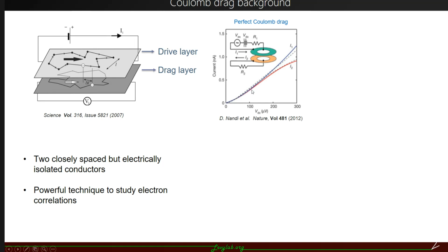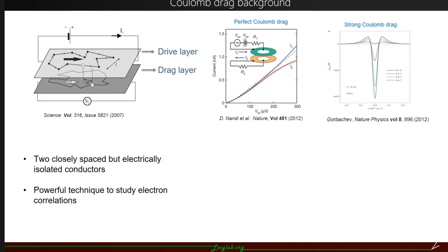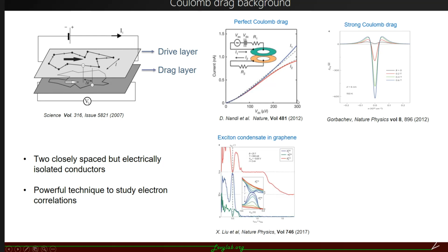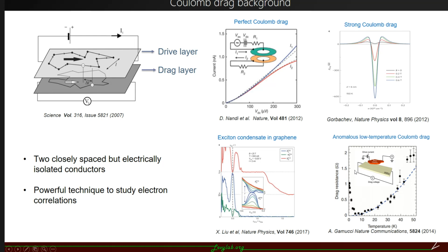A lot of pioneering work has been done in aluminum gallium arsenide double quantum wells. As an example, in 2012, perfect Coulomb drag was observed in an aluminum gallium arsenide double quantum well due to the existence of exciton condensates. Recently, more and more experiments are done in double-layer graphene systems, since graphene allows one to tune the carrier density in a wide range and has less disorder. Energy transfer mechanisms and exciton condensates are found in graphene systems. Besides, Coulomb drag is also performed in hybrid systems, for example, in graphene-gallium arsenide heterostructures. Due to the strong interlayer correlation, the ordinary quadratic temperature dependence expected in a weakly correlated Fermi liquid doesn't apply here.